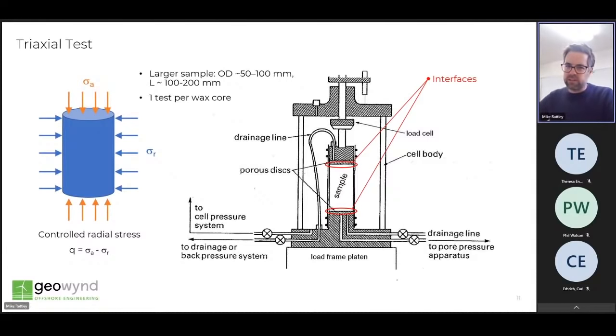The triaxial apparatus includes a cell which allows a confining pressure to be applied via a cell fluid which acts as a total stress. The pore pressure on the specimen can be controlled separately via a back pressure system, allowing the effective stress state of the soil to be controlled prior to shearing.